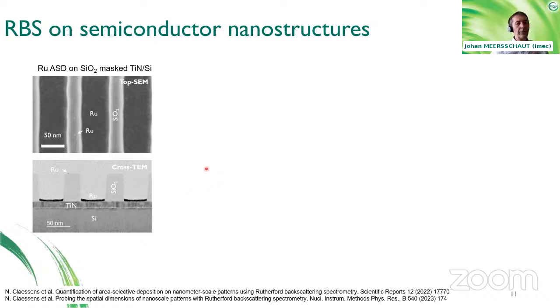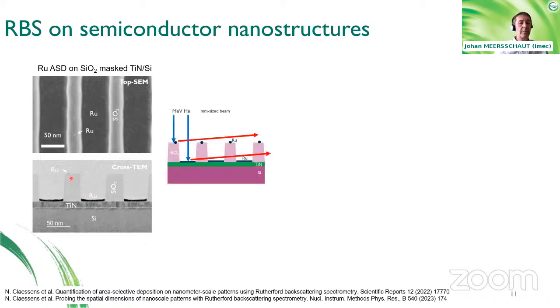The great challenge for area selective deposition is to deposit the material in certain areas, as for example, on the metal layer, and not on, for example, sacrificial or other spacer materials. So here the aim is to deposit the material in between the silicon oxide fins, and not on the silicon oxide fins. So how can we characterize these materials? You see here that, for example, in a TEM, there is a small dot, which might indicate that there is a small ruthenium deposition, but it's very hard from TEM to quantify these materials. So let's do a macroscopic experiment with an ion beam, which has a beam size of the order of 1 millimeter, in which we impinge the ion beam almost vertically.